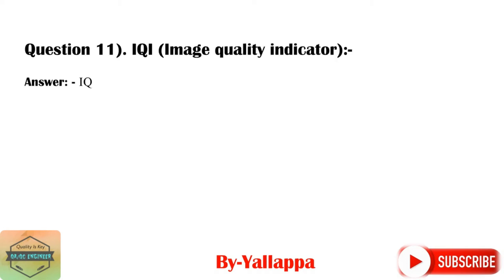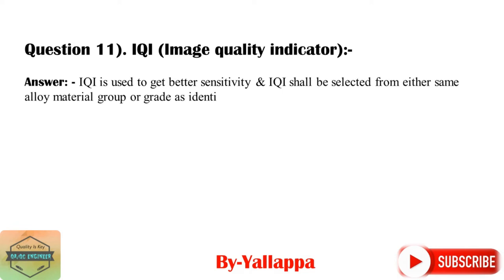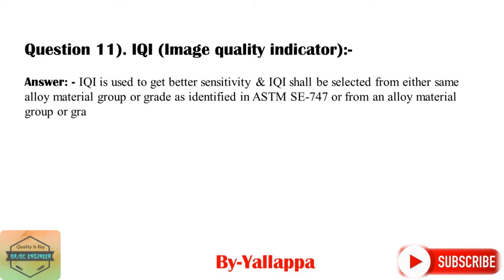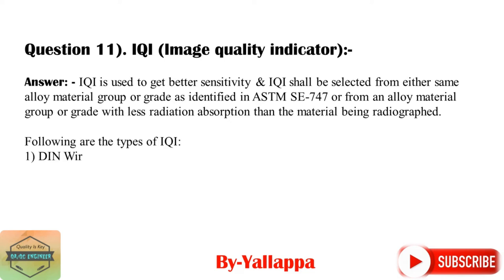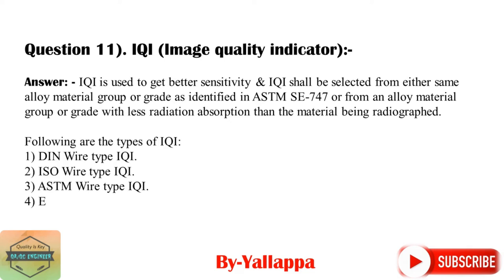Question 11. IQI, image quality indicator. Answer. IQI is used to get better sensitivity, and IQI shall be selected from either the same alloy material group or grade as identified in ASTM E747, or from an alloy material group or grade with less radiation absorption than the material being radiographed. Following are the types of IQI. 1. DIN wire type IQI. 2. ISO wire type IQI. 3. ASTM wire type IQI. 4. E wire type IQI.